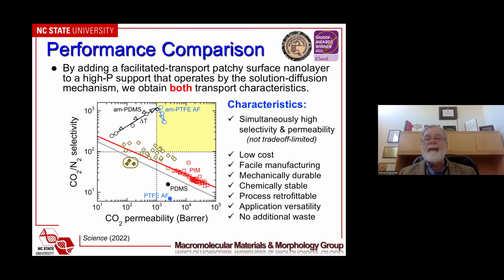So we get simultaneously high selectivity and permeability, low cost because we're using materials that are already used for making membranes, very simple manufacturing in terms of putting these or growing these polymer chains off the surfaces of the polymers. I didn't show you the data, but they are mechanically durable. They're stable over time. Even if they're dried out, they can be rehydrated and reused. They are process retrofittable so that new modules do not have to be designed for these materials. And they can be used in a variety of different applications with no additional waste than is already encountered.